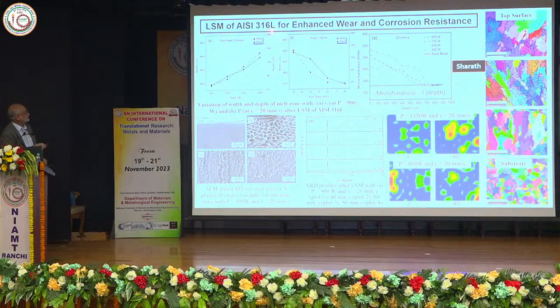So this is a similar exercise with pure stainless steel. Just to tell you about this part, if you look at these orientation imaging mappings, from the top surface you see large areas, and these color codes are only to give you an impression that at the length scale of a few tens of micrometers, there are areas with no grain boundary in between. Even if there's a boundary, it is almost negligible or can be ignored, because the mismatch is so little.